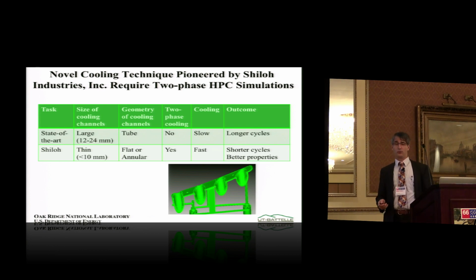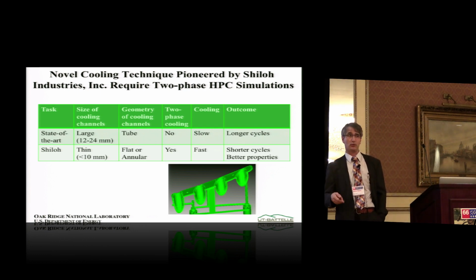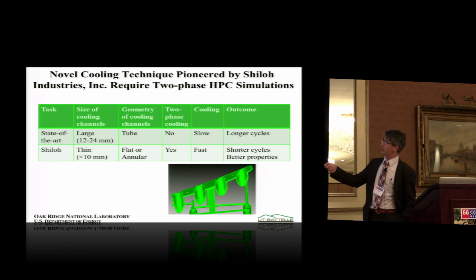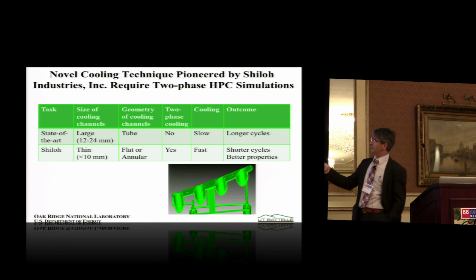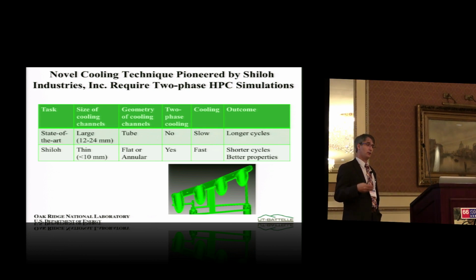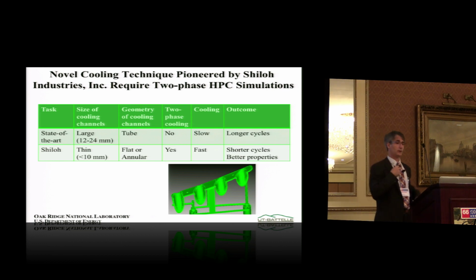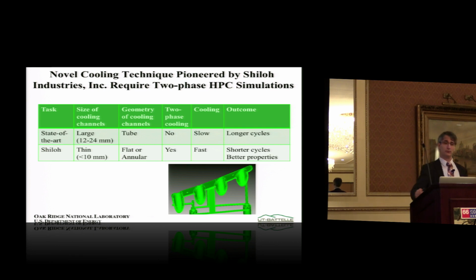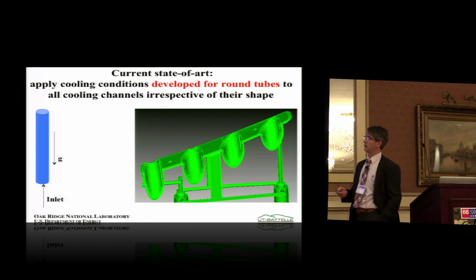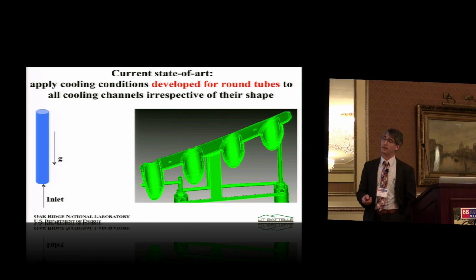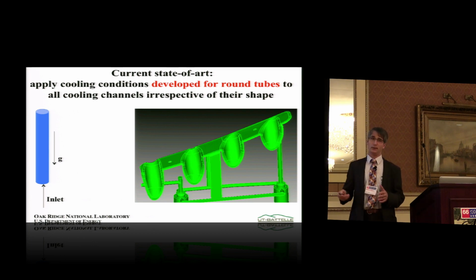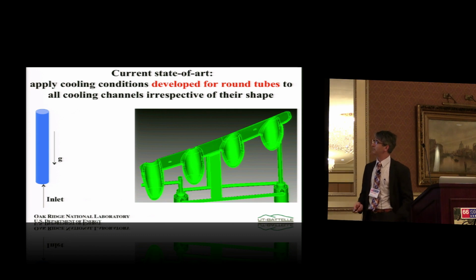So Shiloh proposed to use mini channels, and they can come in different shapes, from being flat or annular in geometry. And the benefit here is brought by two-phase cooling. You have basically boiling of your coolant, and that provides an increased heat transfer coefficient by about 5 to 15 times, resulting in shorter cycles and better properties. The challenge that we faced is that there are not really any correlations available in the literature to prescribe how this flat channel or this inclined channel is going to cool. And this is just one die insert pictured here. The die is actually, let's say, 10 times larger than this little image.